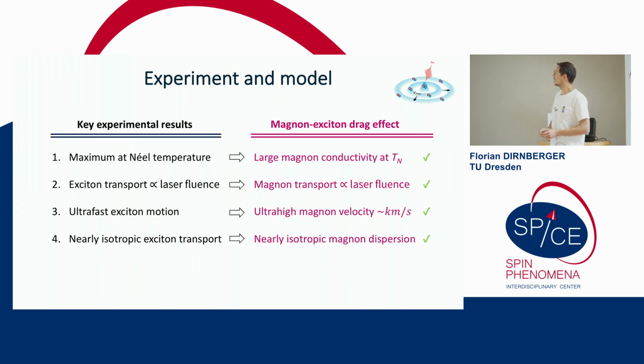And then last but not least, it's interesting to see that the exciton transport should be highly anisotropic because of the anisotropy of the electronic structure. But if you look at what the magnons are doing, their propagation is actually fairly isotropic. So that's how we argue we see isotropic exciton propagation: because the magnons are moving isotropically.